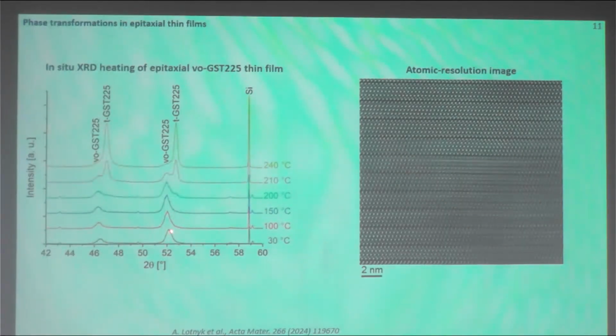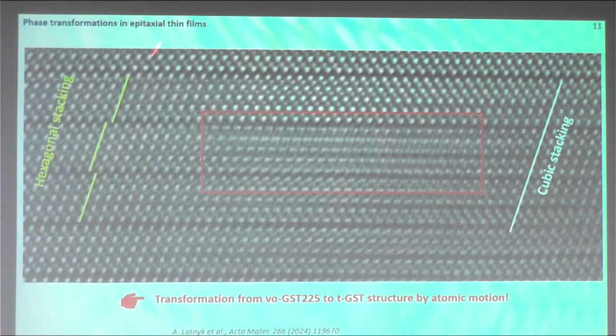So we can see here we start with the vacancy ordered phase, and then at this temperature, 200 degrees C, we observe the formation of an additional peak, which then grows at the temperature 210 to 240 degrees C. And this peak belongs to the TGST phase. This is the stable trigonal phase. So here we can nicely observe the transformation from the vacancy ordered phase to the TGST, the trigonal phase. And here, this is an atomic resolution image that shows you this highly ordered TGST phase, first the vacancy ordered phase here, and then this is the TGST phase, where we know that after the transformation, the structure has hexagonal stacking.